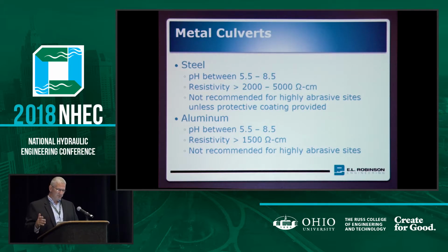Aluminum, as long as aluminum is between about 5.5, 8.5, resistivity is above 1,500, it'll last a pretty good long time. It'll give you your design service life. It should give you 75 years without too much difficulty. Really, really high alkaline isn't very good for the aluminum. So when you get really, really high in alkalinity, aluminum doesn't do so well. So as an example, you probably don't want to concrete encase aluminum pipe, because the alkalinity of the concrete can actually damage the wall of the aluminum pipe.